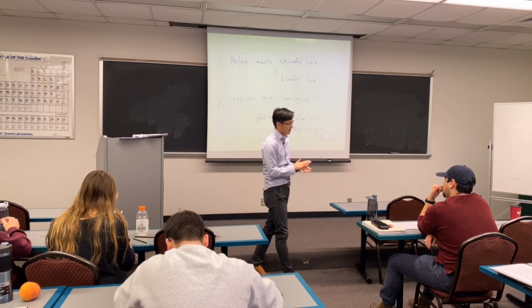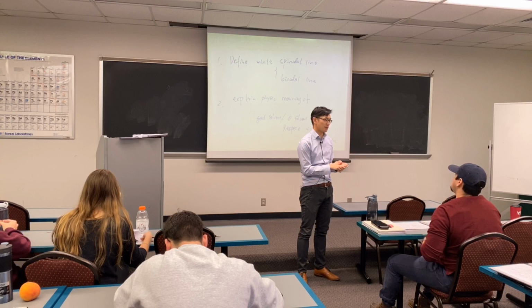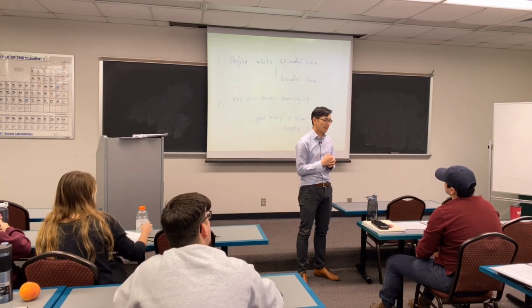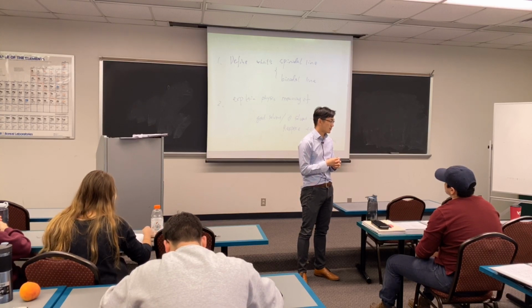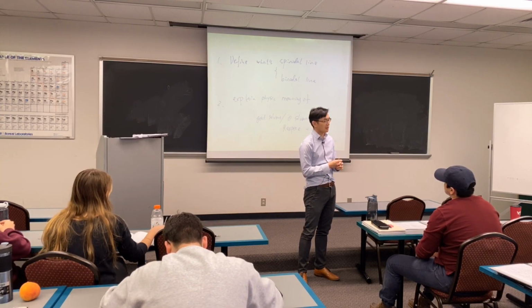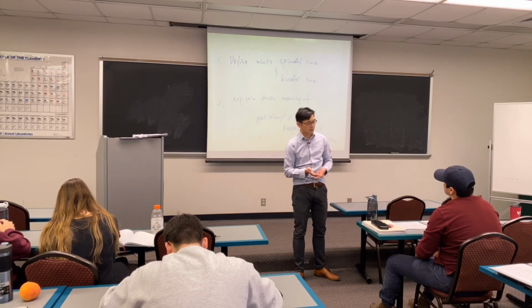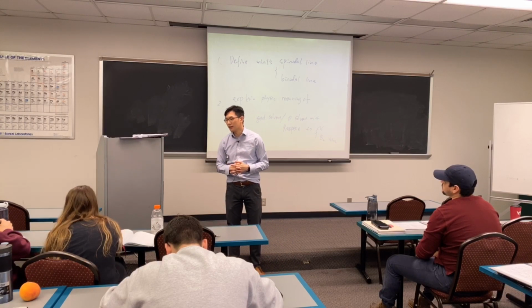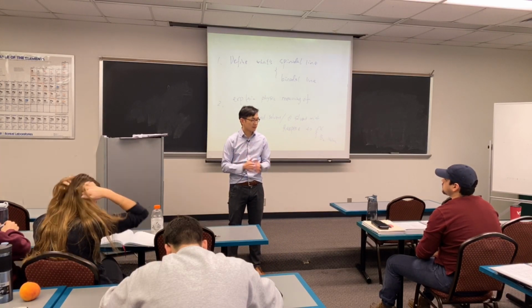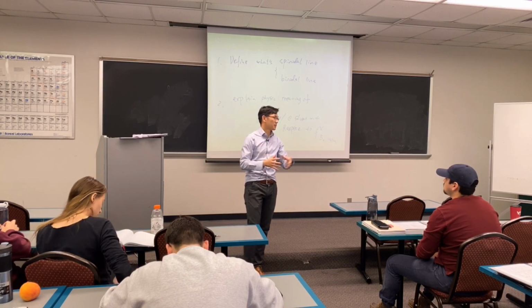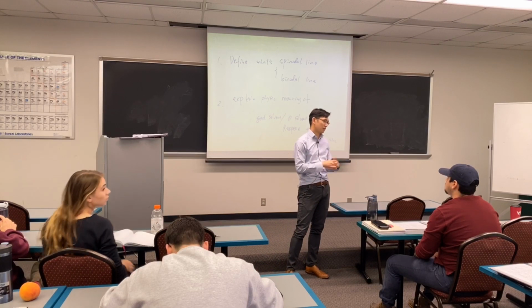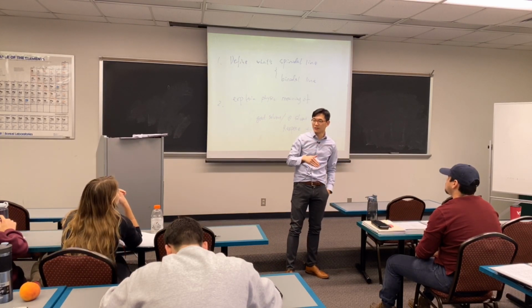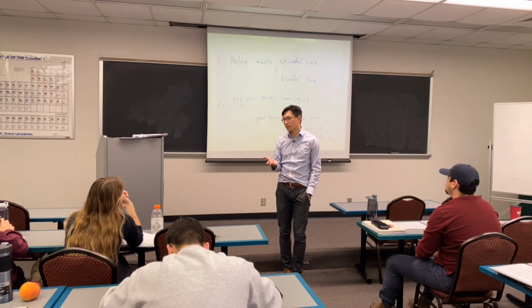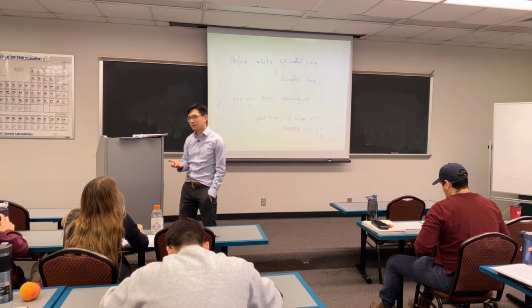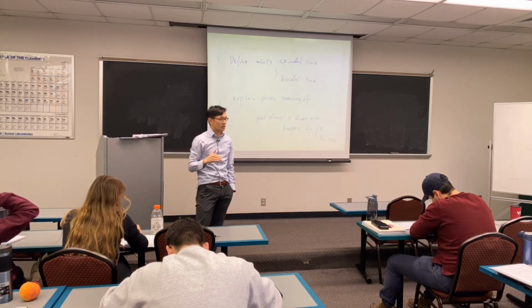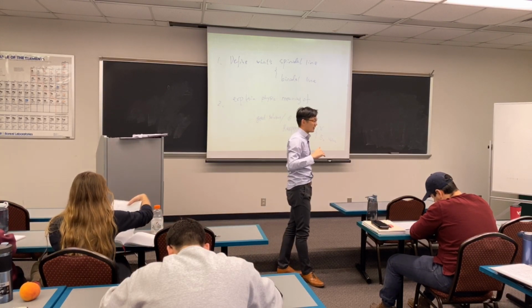But in a short sense, glass transition temperature tells you the temperature at which your polymer chain starts to have mobility. Let's say polystyrene is 100 degrees Celsius. And if you have a second material that is also glassy, which may be polyethylene, also somewhere about 70 to 80. Then if you mix them in the melt, at high temperature in the one phase region, let's assume you can reach that, it will fully mix. If you slowly cool down, it will phase separate. If you think about the UCST phase diagram, right? At high temperature, it will be one phase. At low temperature, it will be two phase. If you cool it down slowly, they will phase separate.